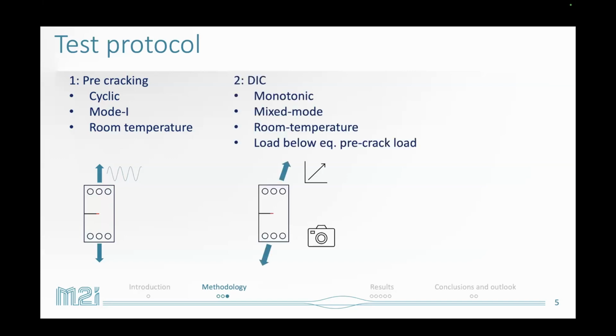Then we do a test in mixed mode, so under a specific load angle alpha. I'm doing a test up to a relatively low load level, so definitely below fracture, more or less in the same region as the pre-crack load. We do this to be able to use digital image correlation to look at the local stress strain field, as already introduced in some of the earlier presentations.